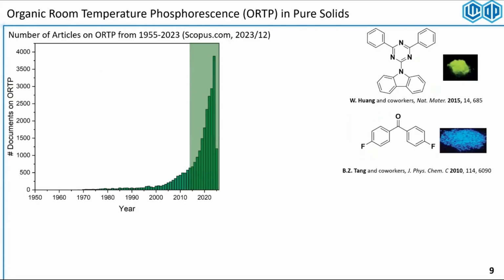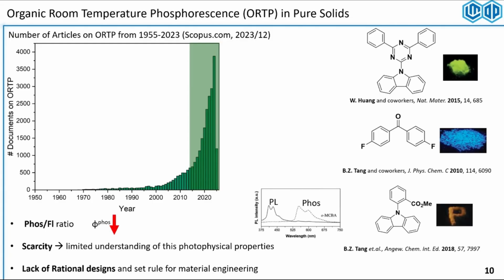And it was until the pioneering works of Ben Zhong Tang and Wei Huang in the field that people started to see these phosphorescent pure organic crystals appearing more and more in the literature. But still, most of them at the time that I was a PhD were suffering from very low phosphorescence to fluorescence ratio. So yes, we could see the afterglow in these pure crystals, but you can see, for example, this tiny little emission of phosphorescence in the 500 to 600 region as compared to the fluorescence.